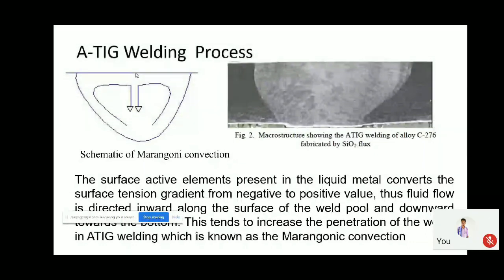So what is happening, sir, actually? For example, when we are doing the conventional TIG welding process, your molten pool will go away like this. Your molten pool will go away like this. But when you are applying a salt, like SiO2, TiO2, as I mentioned here, your liquid flow will go toward this direction. So what is the name exactly? It's called the Marangoni effect. So what is happening? It is converting the negative surface tension to the positive surface tension of the weldment, so that the weldment will go towards deeper penetration as compared to the conventional welding process. So in this case, even at lower current, you are able to achieve the maximum depth of penetration. So that is possible with the ATIG welding process.